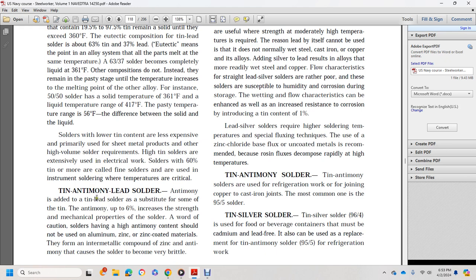Tin-antimony-lead solder. Antimony is added to tin-lead solder to substitute for some of the tin, with up to 6% antimony. It increases the strength and mechanical properties of the solder. A word of caution: solders that have a high antimony content should not be used on aluminum or zinc-coated materials. They form an intermetallic compound, zinc antimonide, that causes the solder to become very brittle.